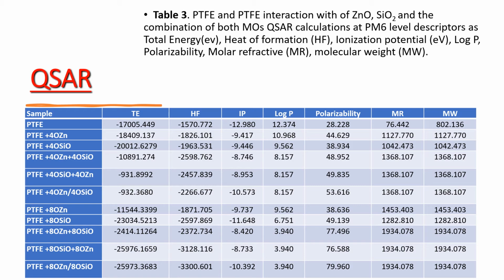Also, the quantitative structure activity relationship calculation, which studies the reactivity and stability of chemical structure by calculating some descriptors such as total energy, heat of formation, ionization potential, log P, polarizability, molar refractivity, and molecular weight. From all data, the most reactive and stable structure was polytetrafluoroethylene with 8 atoms zinc oxide silicon dioxide layer by layer.